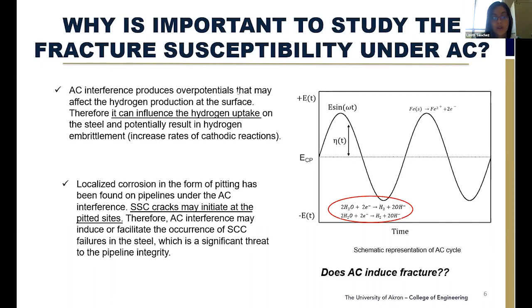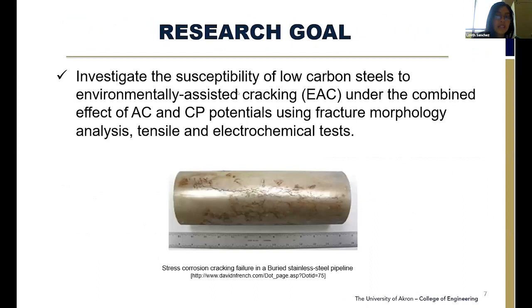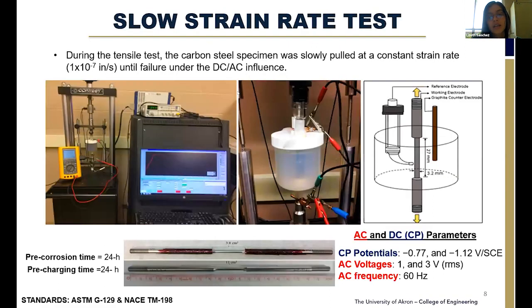The second reason is that in failures due to AC in the pipeline, they have found localized corrosion, the one that I showed before, the little pits. Well, these pits can potentially be sites for crack nucleation. So in that case, AC may facilitate the initiation and propagation of cracking, and that will be really detrimental for the pipeline integrity. So the goal of the research project is to investigate the effect of these combined AC and CP potentials on the cracking susceptibility, environmental cracking, of low carbon steel, pipeline steel, using tensile tests, electrochemical tests, and fracture morphology analysis.